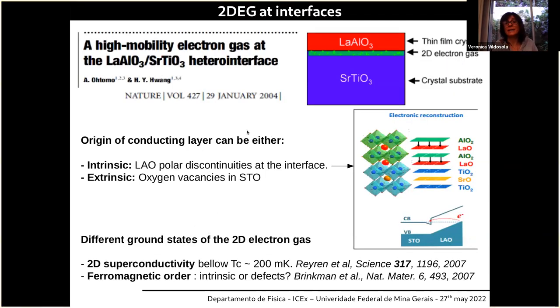The field of generating two-dimensional electron gases at the interface of oxides got some impulse in 2004 with the discovery of a high-mobility electron gas at the interface of this system, the lanthanum aluminate strontium titanate heterointerface. They observed a two-dimensional electron gas between these two insulating materials, and people started to study exactly what the origin of these 2D metallic states at the interface was, in order to be able to control the emergence of this metallicity in two dimensions.